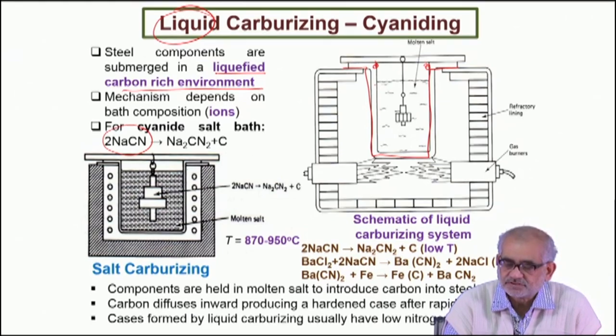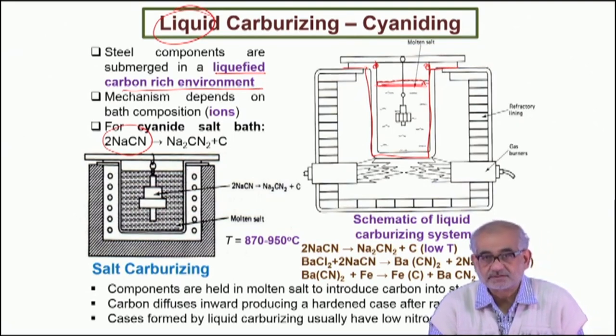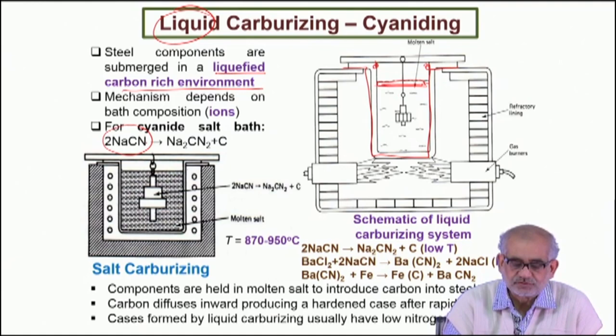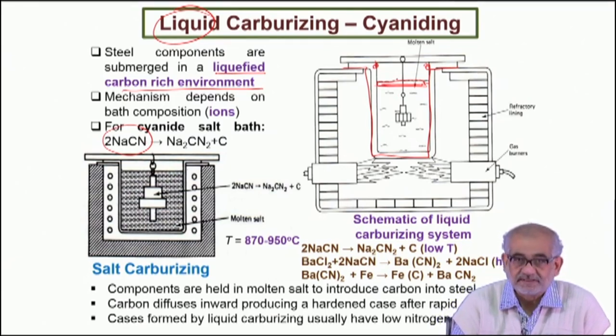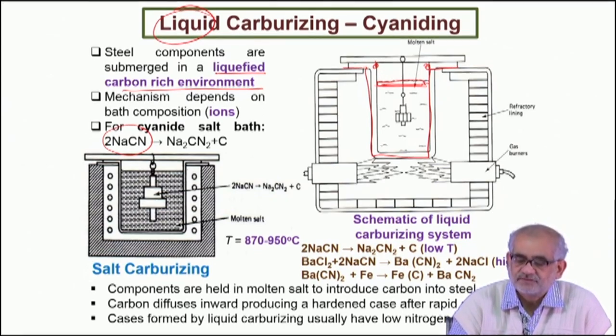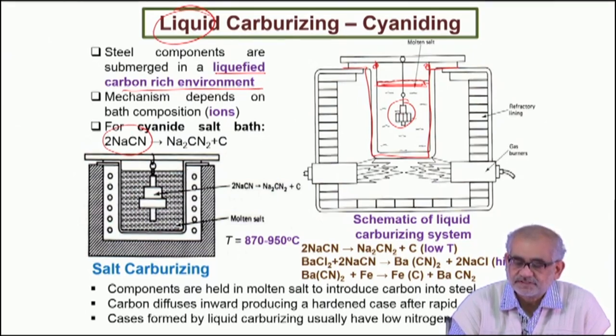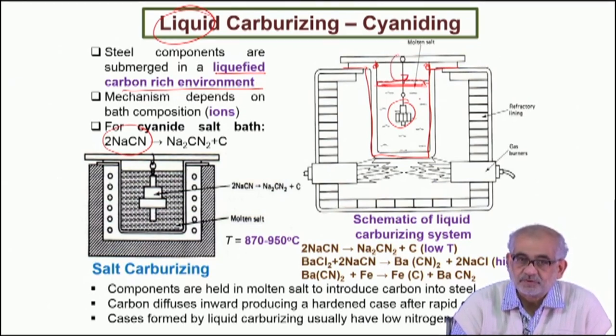As a precautionary measure, the top layer is also covered with charcoal so that whatever dissociates from sodium cyanide does not go into the atmosphere, as it is a highly toxic gas. This is basically a salt bath in which the sample is immersed or dipped inside. The liquid covers the surface of the solid sample from all sides; the sample is usually suspended from the top, with a provision for rotation to create agitation within the bath.